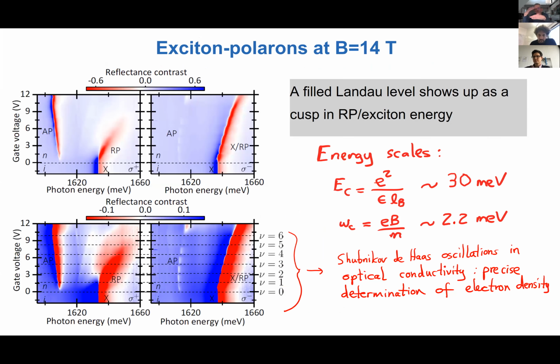So one possibility is to treat the system as a parallel plate capacitor. Once you have charges in the TMD, you can say that, okay, now I have two quasi-metallic layers and the geometric capacitance should determine the electron density as a function of the voltage, which works quite well. But there is a more elegant way of demonstrating it, and that is to look at exciton polarons at very high magnetic fields. And what you see, for example, here, is that the polaron spectrum shows these cusps where the energy shifts to the blue and the line width of the exciton narrows down, okay? And these are separated by exactly the degeneracy of a Landau level.